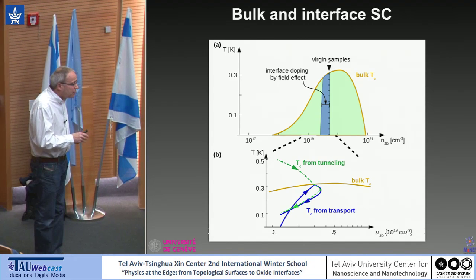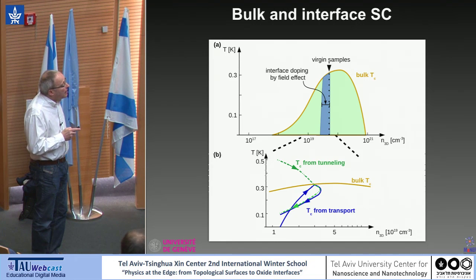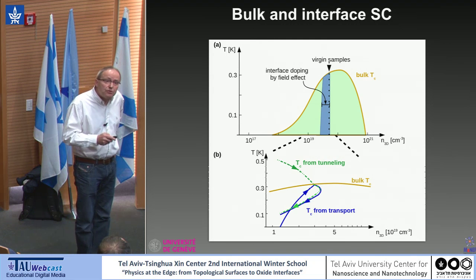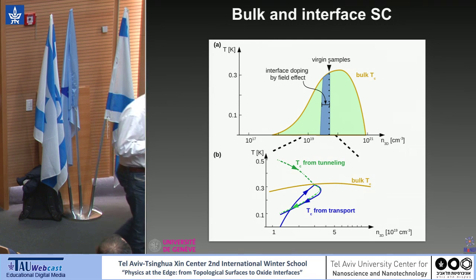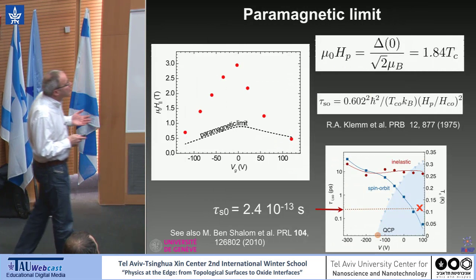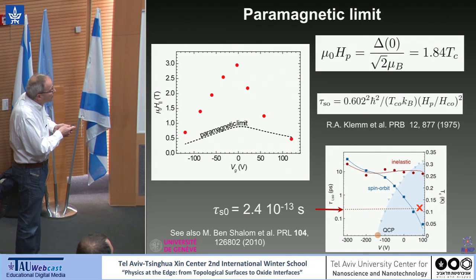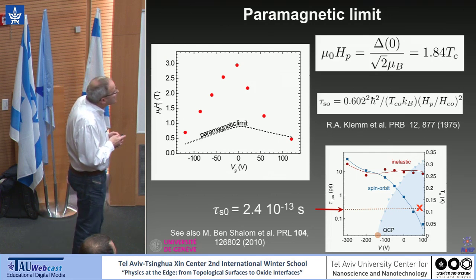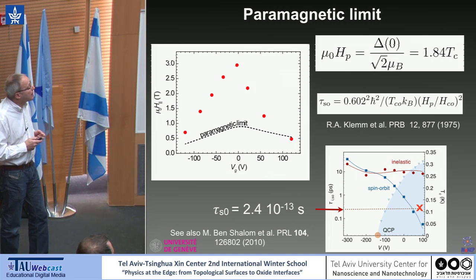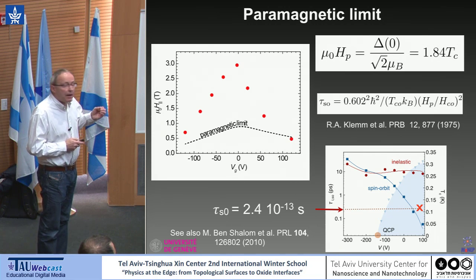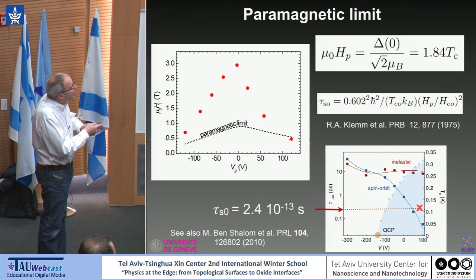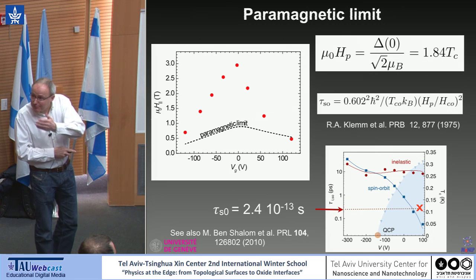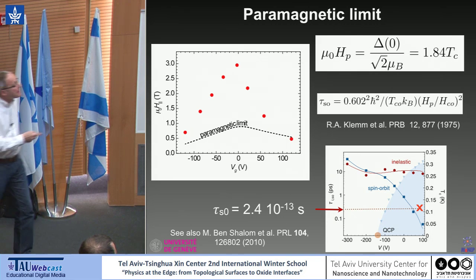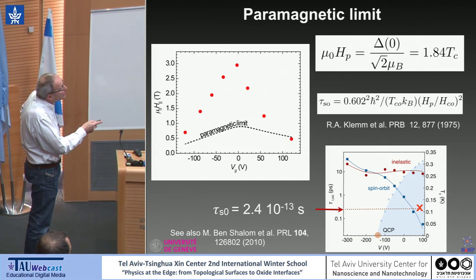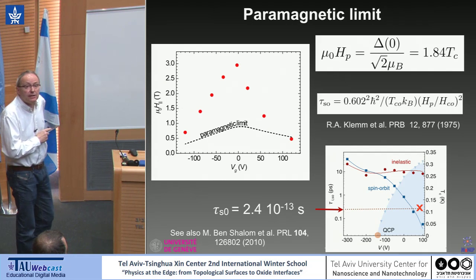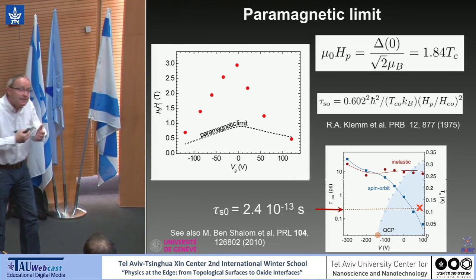Now, to finish with superconductivity, let me just mention one thing, coming back to spin orbit. Because we have a strong spin orbit in the system, in principle, superconductivity should be affected by spin orbit. The only thing I can mention here, and I should also mention the work of the group of Yoram Dagan, is that they measured the parallel field, which goes way beyond the paramagnetic limit. So this is the paramagnetic limit, this is the parallel upper critical field, and from work, I guess, from Stanford, from Beasley, Klemm at the time, there is a way, if you know this ratio between the paramagnetic limit and what you measure, to go back to the spin orbit scattering time, which is the one you would need because spin orbit can enhance this parallel field.